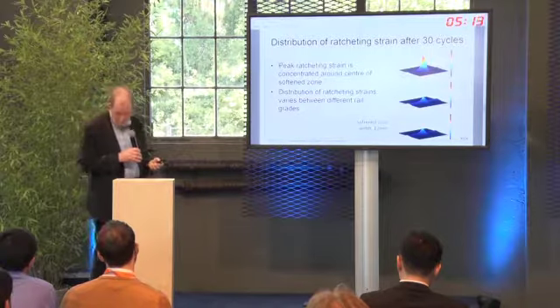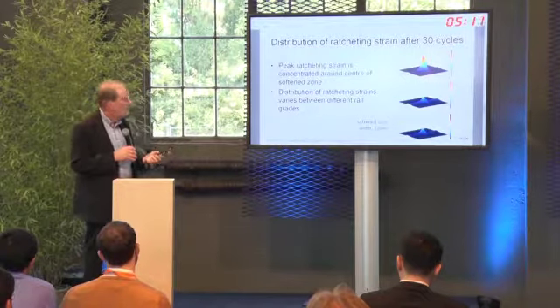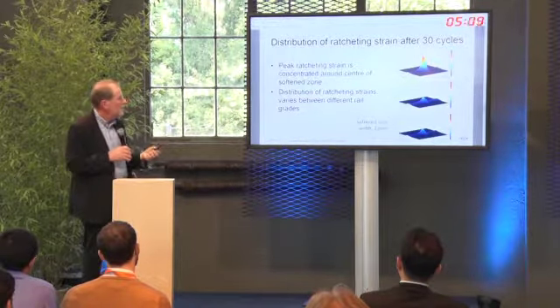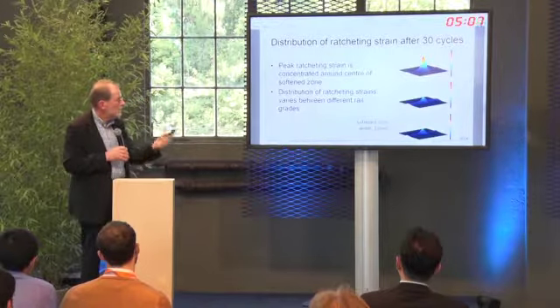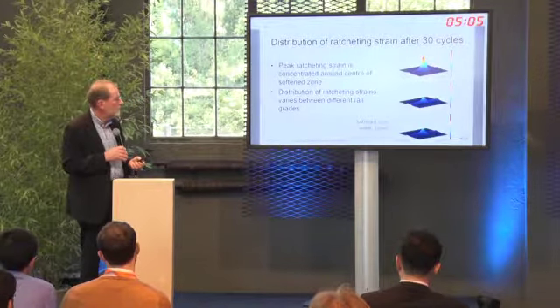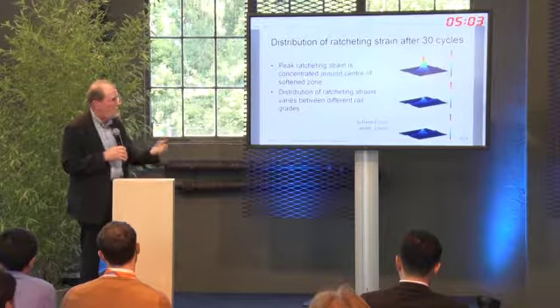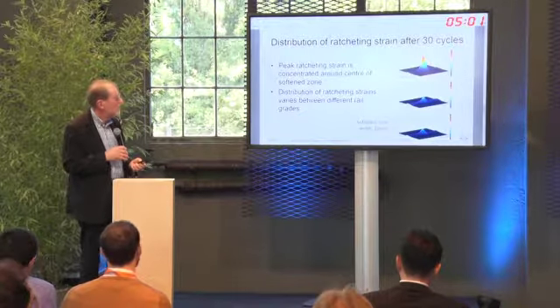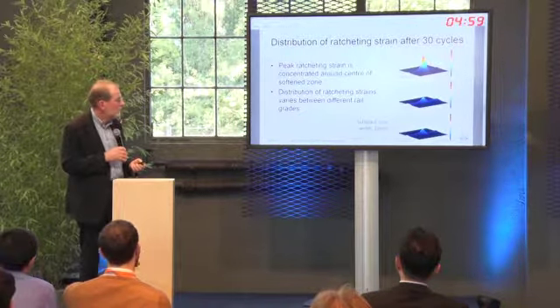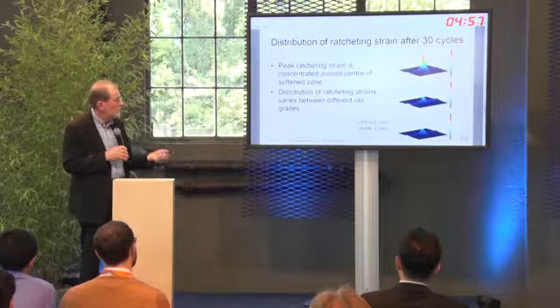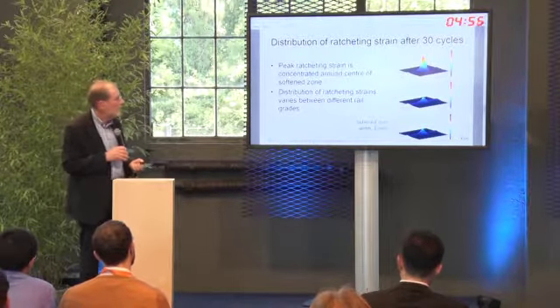This typical result is the peak ratcheting strain after 30 cycles for the softened zones in those three rail grades at a 12mm wide heat affected zone. So you can see that there is quite a bit of difference between the two rail grades, the lower carbon one having the higher ratcheting strains.